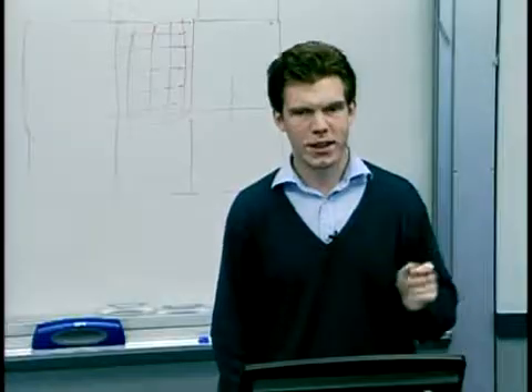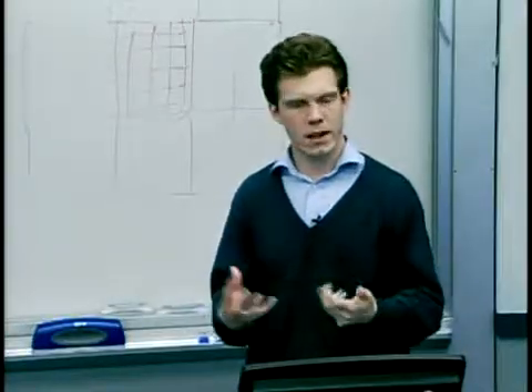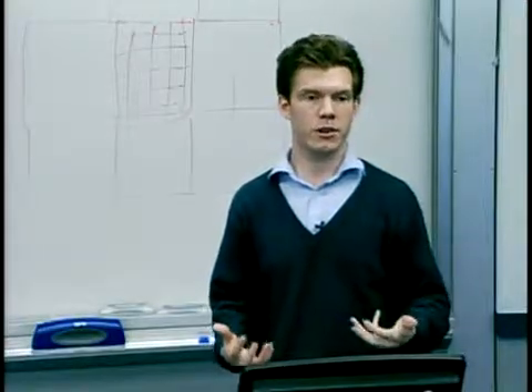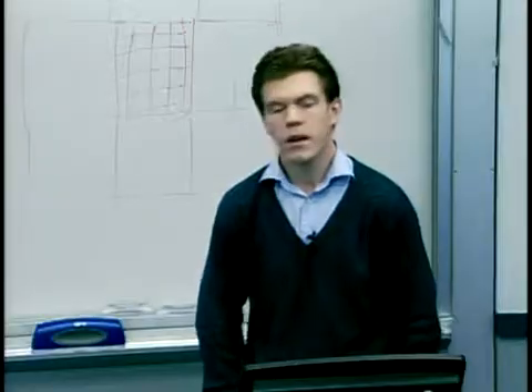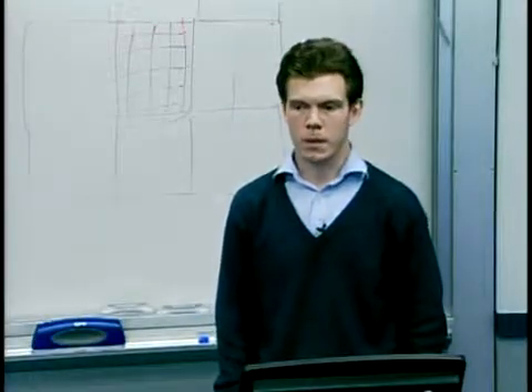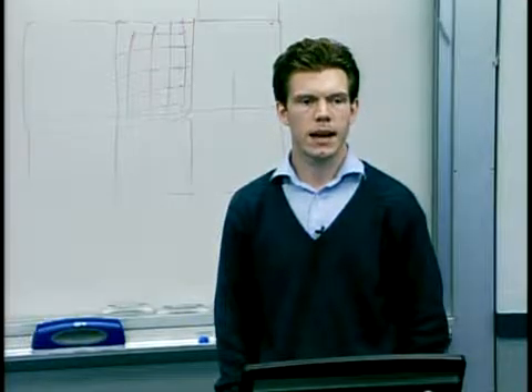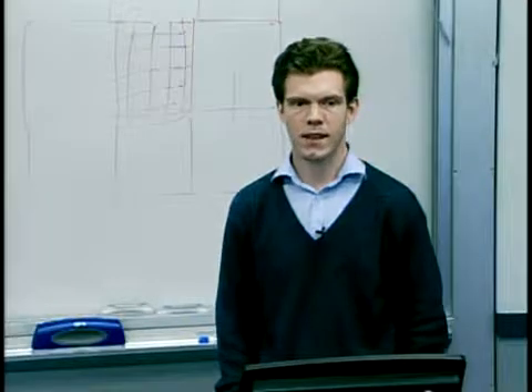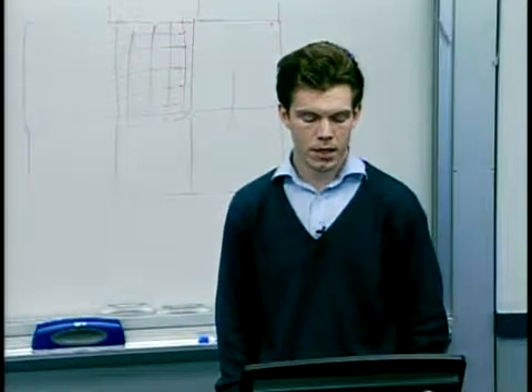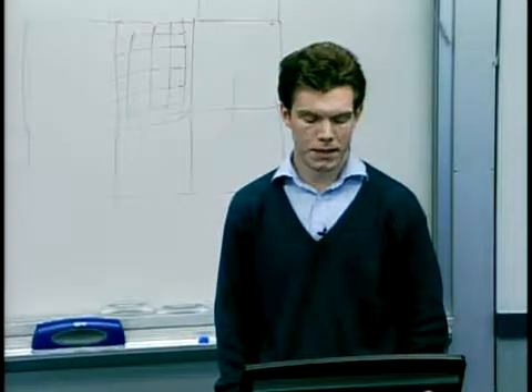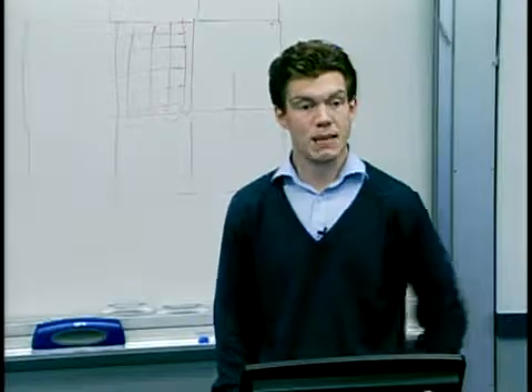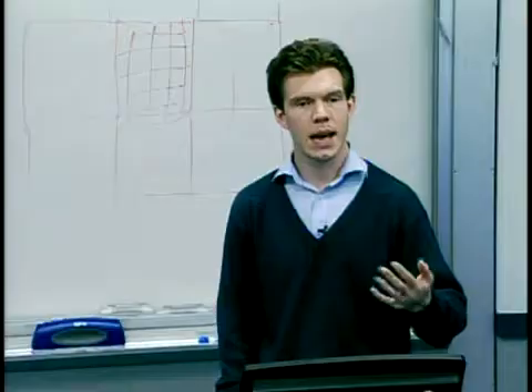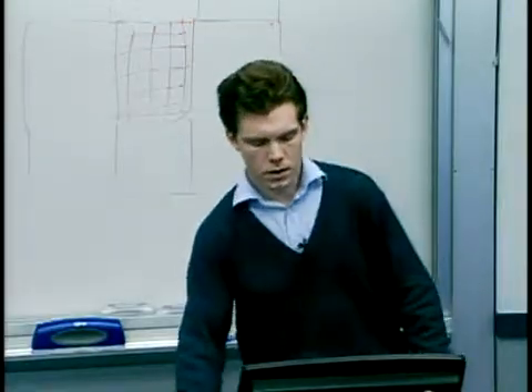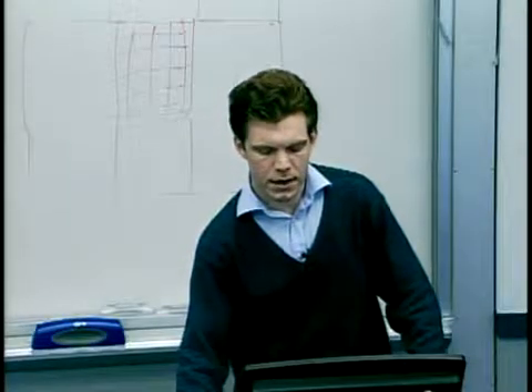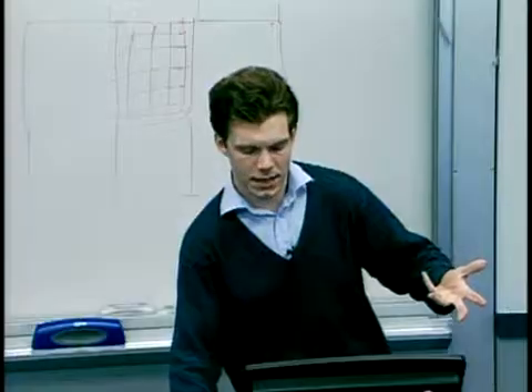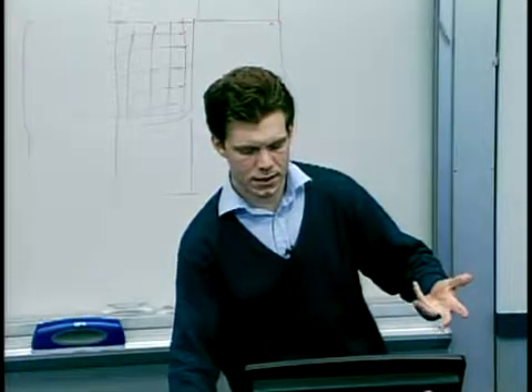Now, I said before that this rubbery model is really only useful if the hold time is comparatively short. And often that's the case. You want the cycle time to be as short as possible. So if you can get the material into a state where you press hard enough, you get the deformation almost instantaneously, then that's great. But in a lot of cases you can't do that, and you do get this plastic flow. So what I show here is the evolution of an embossed topography over time as we hold the load at high temperature. The black symbols down here show what happens if you start cooling the material down as soon as the load reaches its peak. So material is bowing into the cavities but hasn't gone very far.